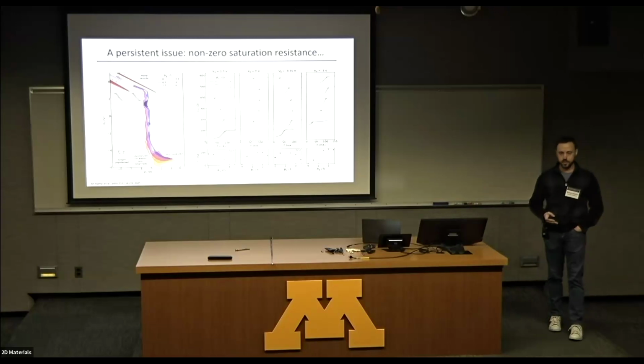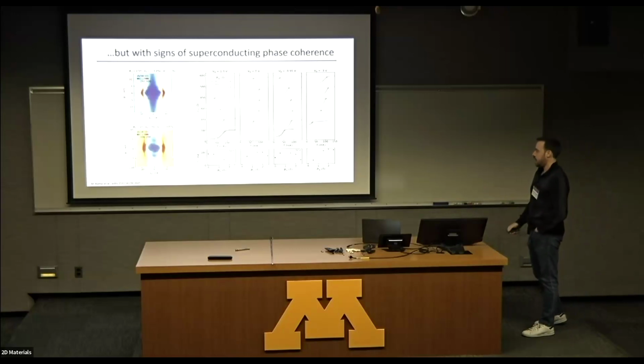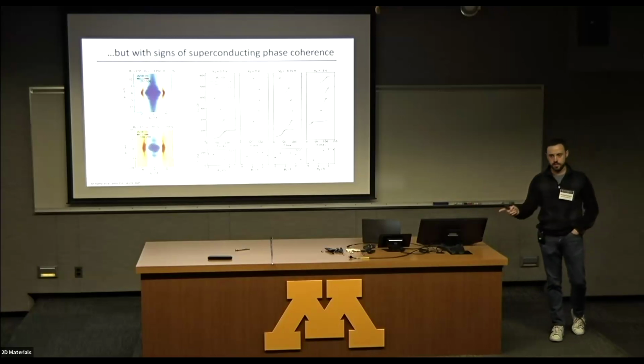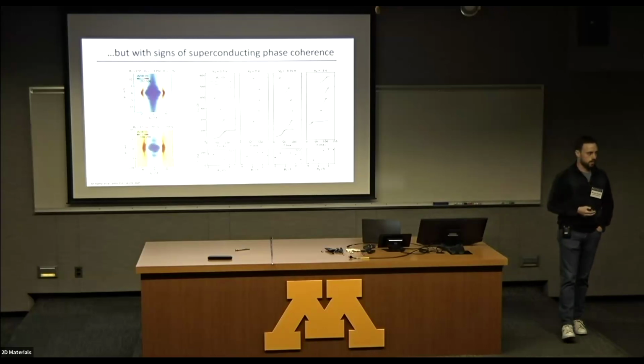It's not any universal number. Sometimes it's just a few ohms. Sometimes it's hundreds of ohms. But to the best of our ability to measure it, it's distinctly not zero. And this is despite the fact that if you make measurements of the differential resistance versus DC current in out-of-plane field, you can see oscillations in the differential resistance that are periodic in field that very sharply resemble Fraunhofer oscillations.